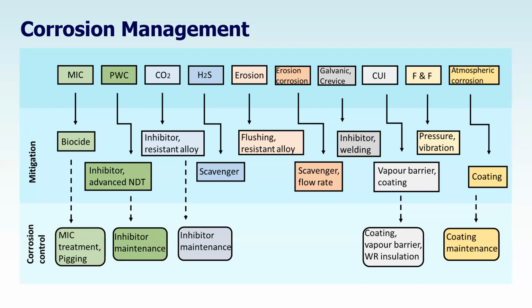H2S and oxygen corrosions are mitigated with applying H2S scavengers and oxygen scavengers, and erosion corrosion by controlling the flow rate, respectively. Erosion is mitigated by doing sand flushing periodically and selection of suitable material with high resistance. Galvanic corrosion is mitigated by applying an inhibitor, or otherwise we can separate the 2 different materials with separating layers such as rubber sheets or a coating.